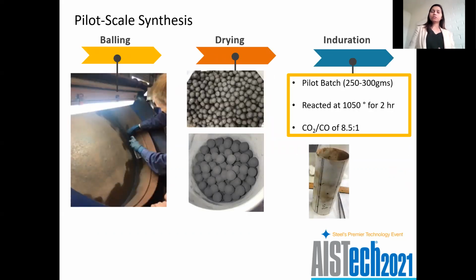The pilot synthesis was done with the magnetite concentrate from U.S. Steel and limestone ore. The limestone was crushed to 45 microns; the concentrate was already at 45 microns. They were mixed together, and 8.5% water was added. Then we made the seeds, followed by balling. The balls were mostly plus 10 mm in size, and the green balls were dried at 110 overnight, followed by induration in a vertical tube furnace at 1050 for 2 hours.